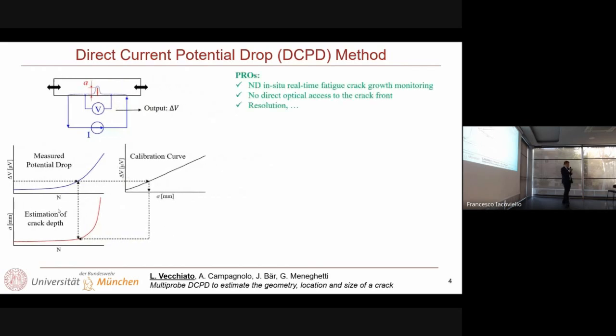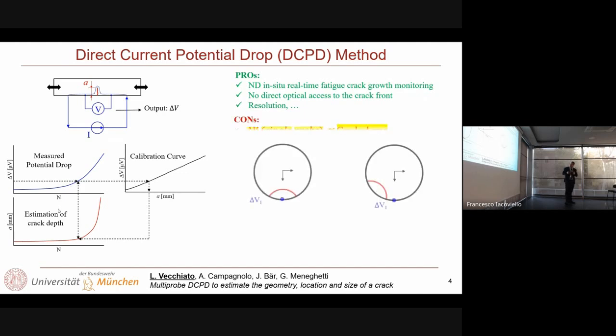I'm pretty sure that many of you are familiar, and we know that this method is non-destructive, in situ, real time. It has a very high resolution and is quite widespread when fracture mechanics tests are considered. On the other side, it has one main problem. When we apply the potential drop in its standard way, we're just using one single probe, so just measuring one potential drop on the specimen, we have just an idea on the size of the cracked area, or the ligament section.